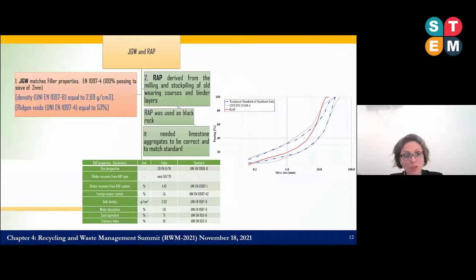So jet grouting waste matches filler properties, in compliance with EN 1097 standard, because all material passed the 2 millimeter sieve. The RAP used derived from the milling process of the wearing course and binder layers, and it was used as black rock. It means that the solidified bitumen that covered the aggregate and helped to make a bound structure was not reactivated by rejuvenators. The grading curve of the RAP, as you can see on the right side of the graph, needed to be corrected because it does not perfectly match the standard. And so we have added limestone aggregate to match the standard, as you can see.